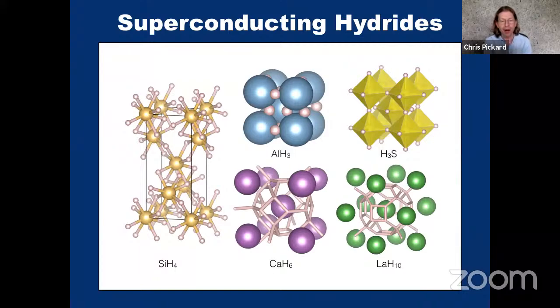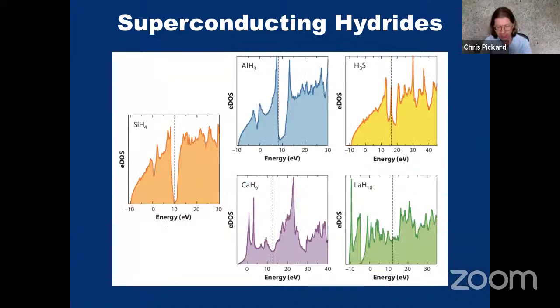In the intervening time, Yangming Ma also proposed very high temperature superconductivity in calcium hydride. This hasn't been found experimentally yet, but then working with Yangming, we predicted superconductivity in yttrium hydride and lanthanum hydride. And that's where the story starts to get really quite exciting. So here are the density of states of these structures. You can see what I might have thought was quite special about the aluminium hydride, because you've got a very sharp peak in the density of states at the Fermi level. In the hydrogen sulfide, it's a very special structure with a very strong peak at the Fermi level, which maybe would be unstable to some structural distortion, but it isn't. And it turns out it's unstable to superconductivity. That's the mode that it finds to lower